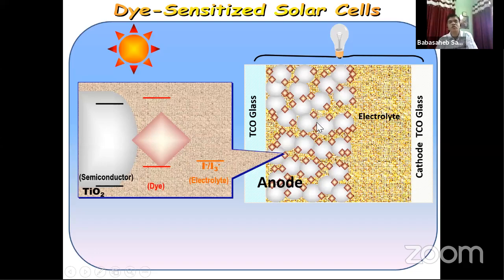Usually TiO2 is used for the dye-sensitized solar cell, and these are the P25 TiO2 nanoparticles procured from the Degussa company. These are interconnected nanoparticles with a very high surface area. The basic requirement for this type of material is that it should have a wide band gap, so that the visible light falls on the dye molecules, which form a monolayer coated on the high surface area interconnected nanoparticle network. Then you place the liquid electrolyte and a back contact of platinum coated on the TCO layer.